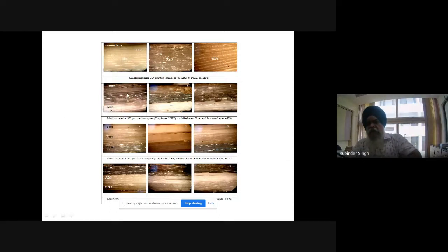Now you see this picture. Here, the lowest layer was ABS. Over that I have printed PLA, and then over it I have printed HIPS. If I print the material like this, this PLA has a side flow of the material. Because of the side flow, you can see here there is some globule formation. Because of this, the strength of the part is reduced.